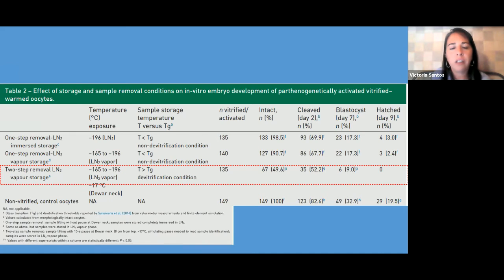We can see here the effect of the 2-step removal from a vapor nitrogen storage. The temperature here was above the TG, and the hatch at day 9 gave a survival of 0. So the other 2 treatments, which were samples exposed to temperatures below TG, there were no significant differences, and there was survival.